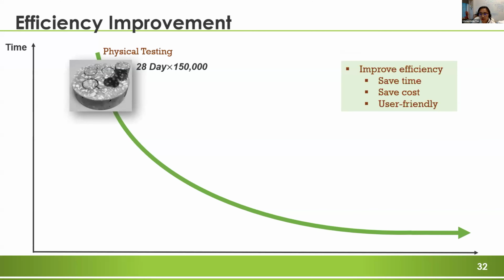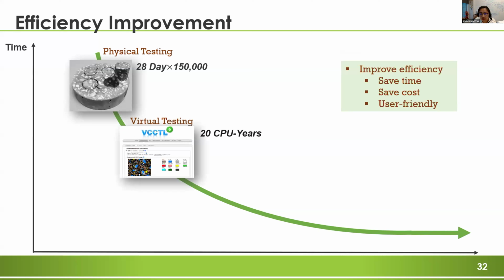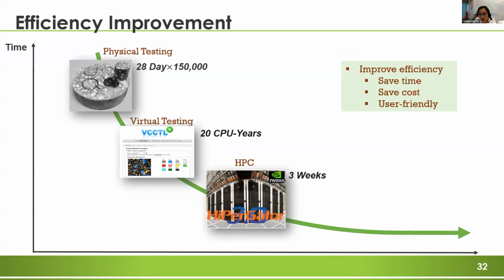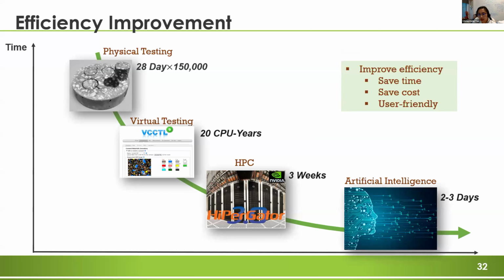For example, if we search optimal solutions by conducting physical tests, it requires about 28 days per test, which is about hundreds of years to finish. And if we apply the user interface of the virtual cement testing lab, it requires about 20 CPU years to finish the simulation. And if we run the simulation on a high performance computing cluster with parallel computing, it takes about 3 weeks. And if we apply AI optimization and machine learning algorithm, we can find the optimal solutions based on user requirement within 2 or 3 days. So this computational framework significantly reduces the time and cost, and is also very user-friendly for the cement and concrete industry.